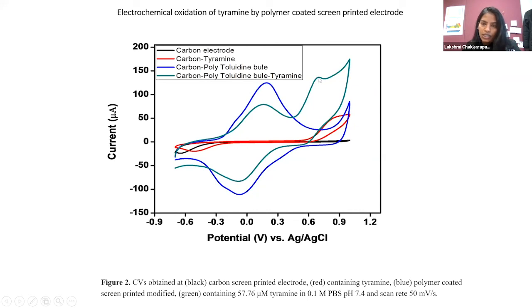So here you could see the oxidation peak of tyramine appeared at 0.65 volt. When compared to the bare electrode, the modified electrode shows the sharp peak of tyramine with a high current response. But the bare electrode doesn't show the sharp peak, and the current response is not countable. So that's why we feel that the electrode is capable of sensing tyramine.